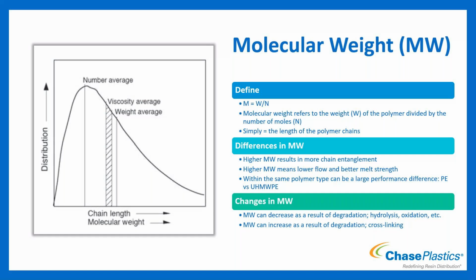And so differences in your molecular weight, a higher molecular weight, so longer chains, is going to result in more chain entanglement. So they're going to get tangled within each other. It then allows for better melt strength. So if you hear us say higher molecular weight or lower flow, you're going to see generally a better melt strength. That's why if anyone listening is in the extrusion game, you want a low flow material. It needs to have the good melt strength, and it needs to have that chain entanglement to really hold it together as it's being extruded. And so molecular weight plays into that.